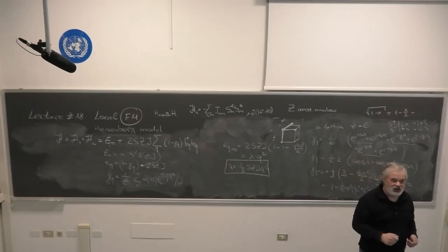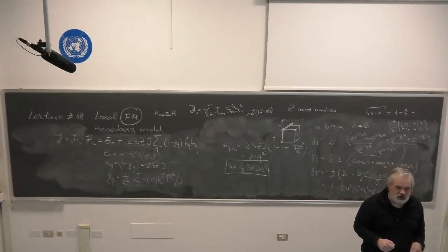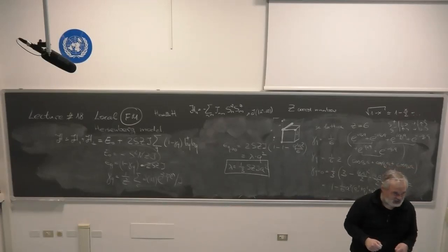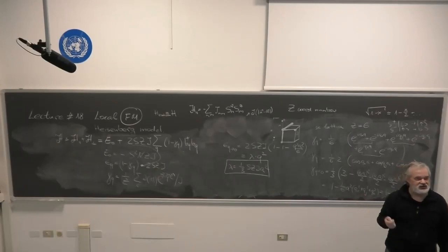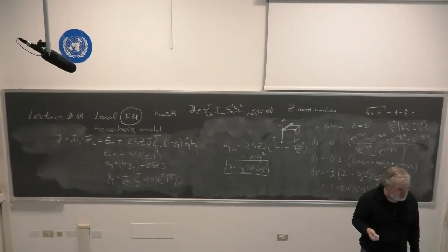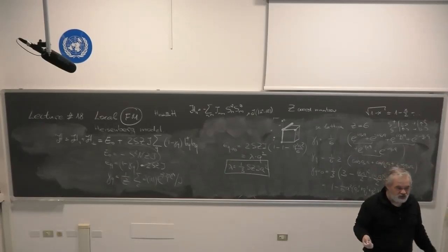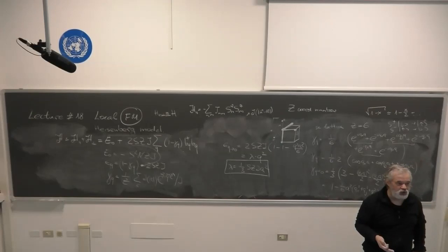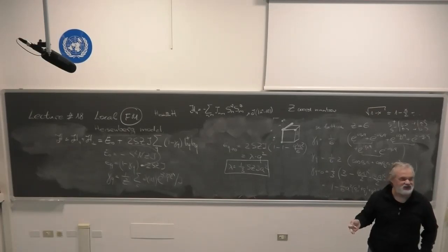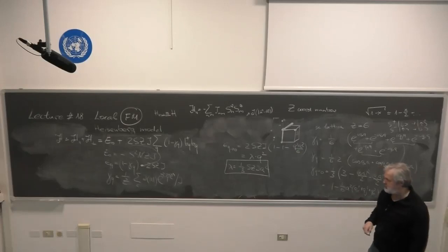On the next lecture on Wednesday, we will see that there is an analogy between Bose-Einstein condensation, superfluidity, and the ferromagnetic and antiferromagnetic cases. We see in this regard that the dispersion of ferromagnetic magnons is the same as for an ideal Bose gas. It's q squared. We will see that the dispersion for antiferromagnetic magnons is linear in q. It's like acoustic phonons, sound, and therefore it resembles the spectrum of a weakly non-ideal Bose gas. So ferromagnets are similar to the ideal Bose gas, antiferromagnets similar to the weakly non-ideal Bose gas.